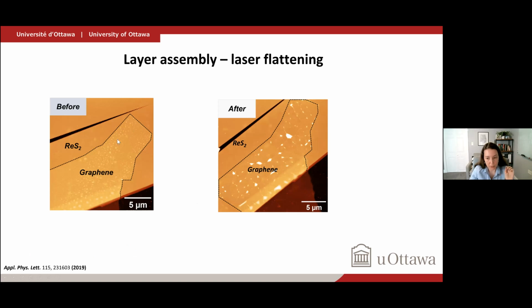I'm showing you here more clearly. So this was before we did this laser raster flattening, and this is after. As you can see, now we've improved the surface by having all these tiny little bubbles now coalesce into larger bubbles and leaving behind microns of free and good interface between the two materials.